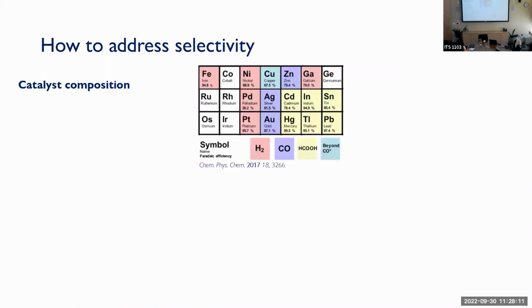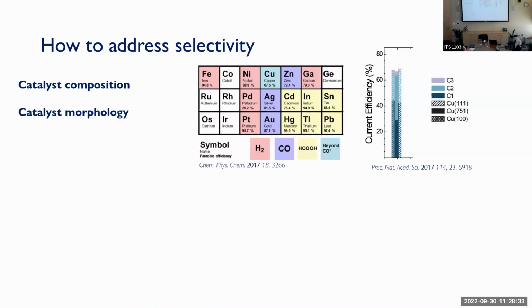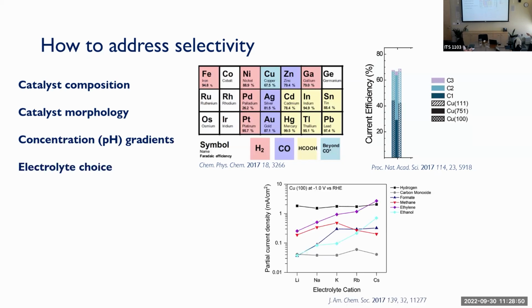We looked at different catalysts, or different catalytic elements that are out there. And what you can find is that there is only one element that can really go beyond CO, which is copper. And then there are other elements that make hydrogen preferentially, or CO preferentially, or formic acid. We can vary the catalyst morphology, and varying the catalyst morphology can actually lead you to be more selective. We can look at different pHs. Higher pHs are reported to give more C2+ products.